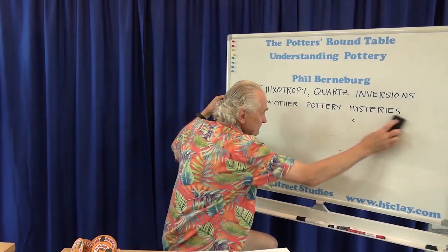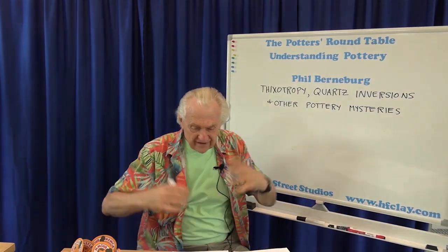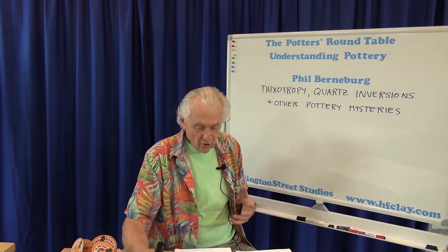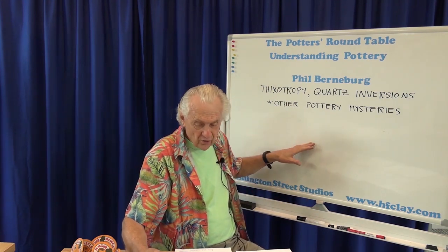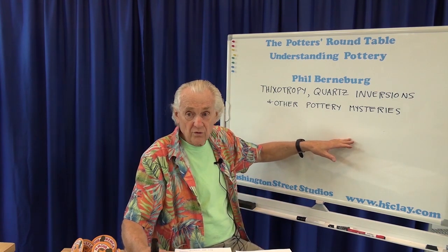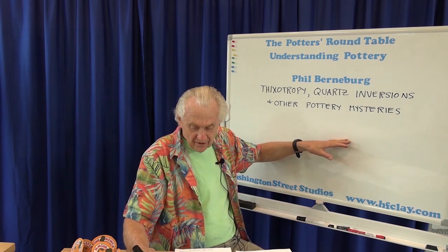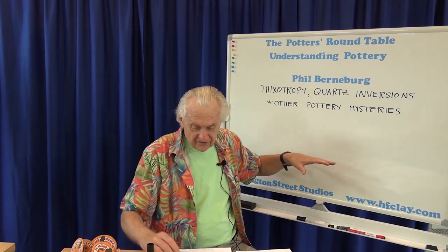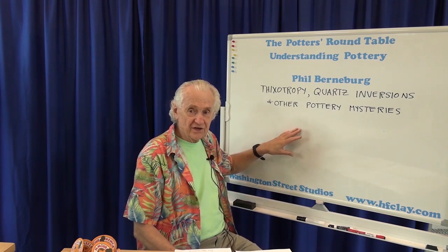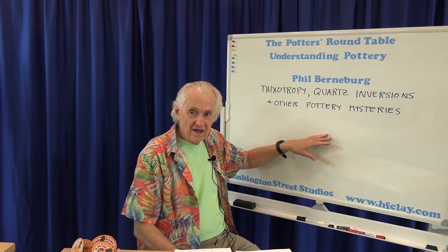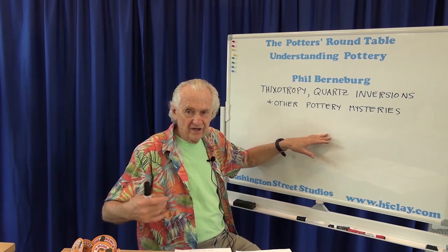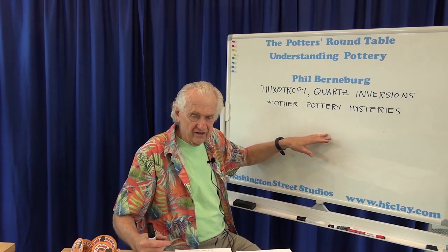when I fire, let's say, a clay body, all the clay bodies contain a lot of silica. So there's silica in the clay itself, and then we add silica as an ingredient. So during the firing, when I heat it up and get to 1,000, the low quartz changes to the high quartz, and the quartz particles expand a little bit. Now, when I get to higher temperatures, some of the quartz can actually change into cristobalite. Okay? There is no cristobalite in naturally occurring clays. It's a very rare mineral by itself. But these forms can change into one another.